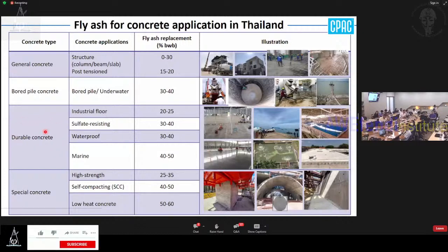And if we talk about durable concrete, as I mentioned, industrial floor, we use around 20 to 25%. For sulfate resistance, we use around 30 to 40%. For waterproof concrete as well as marine concrete, we use around 40 to 50%. For the special ones, like high strength concrete, self-compacting concrete, and low heat concrete, that today I'm going to give you some information on in detail, we use from 25% up to 60%. This is commercial in Thailand right now, and you can see some projects here.